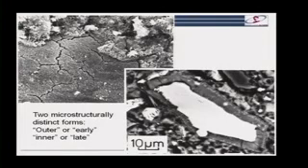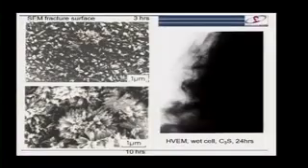And you can see that more clearly in this fracture surface here. This is the dense product. These cracks are actually due to the fact we've dried it out to put it in the microscope. And here we have this kind of sea urchin structure on the surface. Now this filmy product, this product like this, is the product that's forming first.